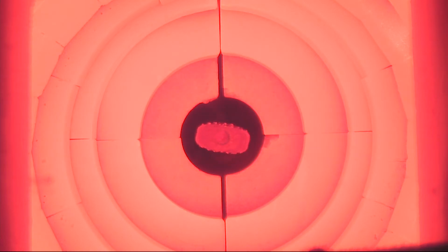Now, she did something right there. I didn't talk about it when she did it, but she took her tweezers, she dunked them in the bucket of water, and she dripped a little water on it. You saw that. You could actually hear it. The water, when it hits the glass in its rigid state, it was probably around 1,000, maybe 1,100 or 1,200 degrees, those water drops create stress cracks. So that's thermal shock. We can use thermal shock to our advantage if you know how to use it, and she does. So she just shocked that constriction, tiny little cracks form, and that tap on the pipe is the vibration that does the rest.